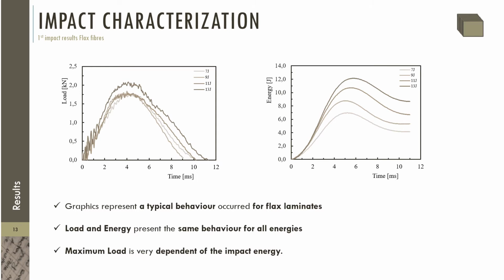The maximum load value represents the value that the composite laminate can tolerate before undergoing major damage, and this maximum load is very dependent on the impact energy. The curves on the left present oscillations that, according to the literature, result from the elastic wave and are created by the vibrations of the material.